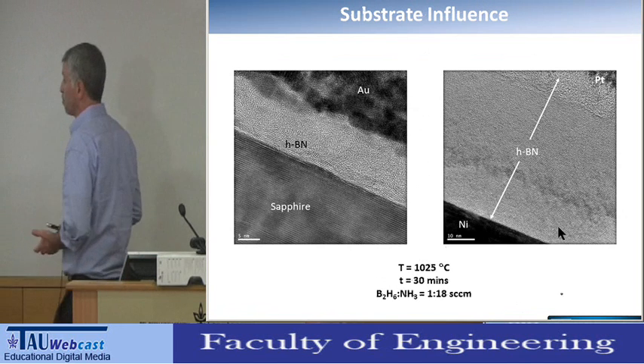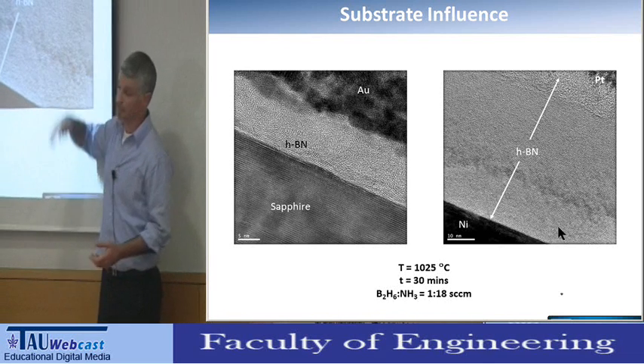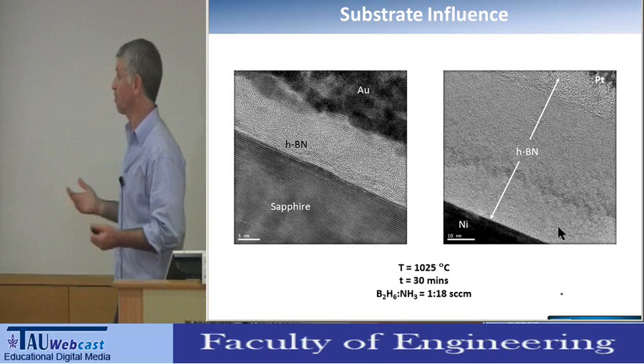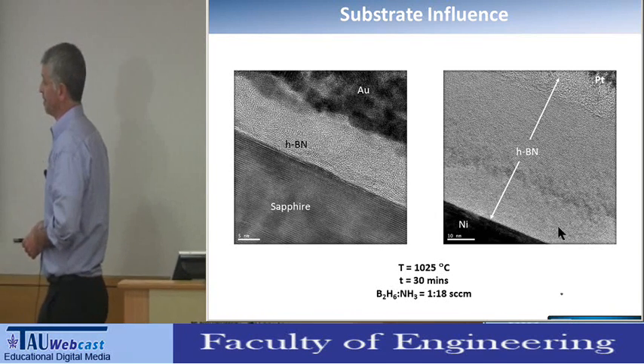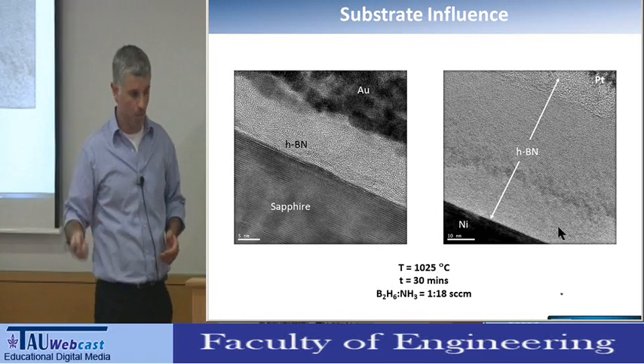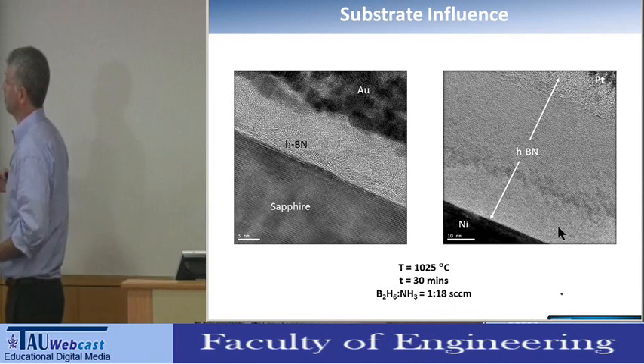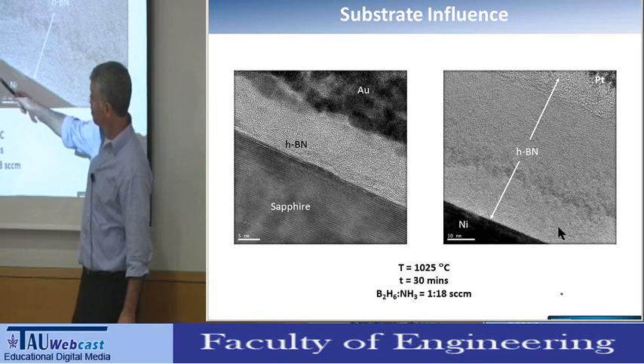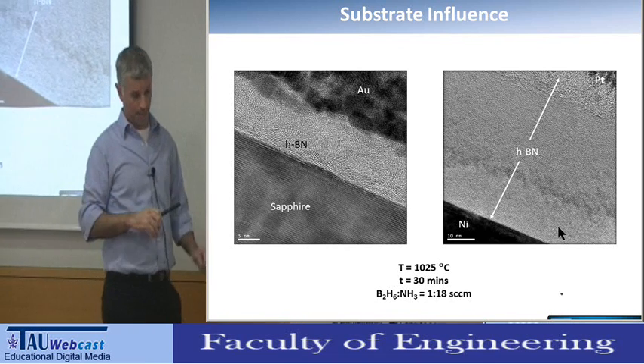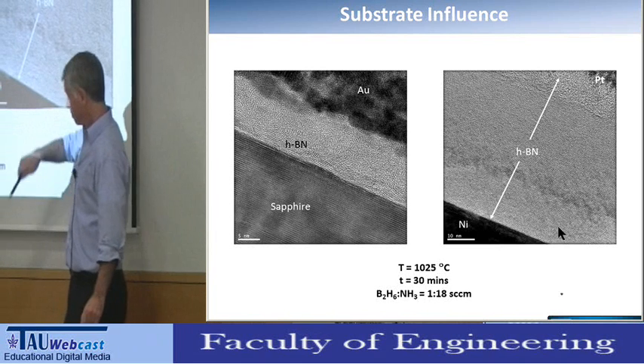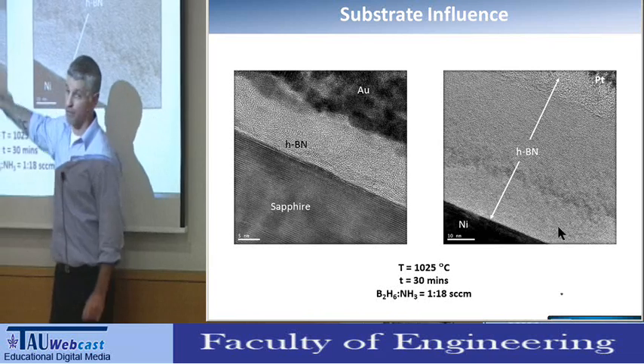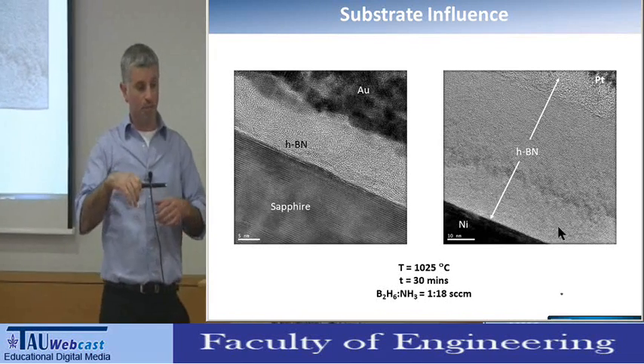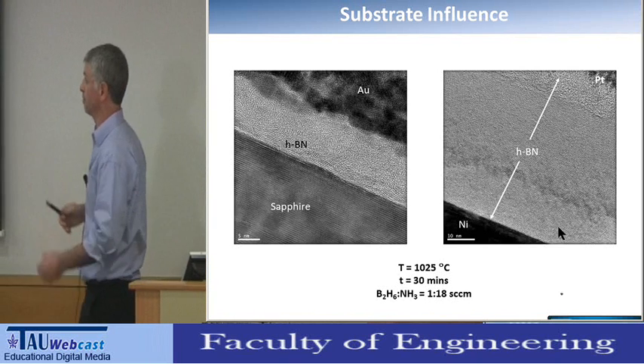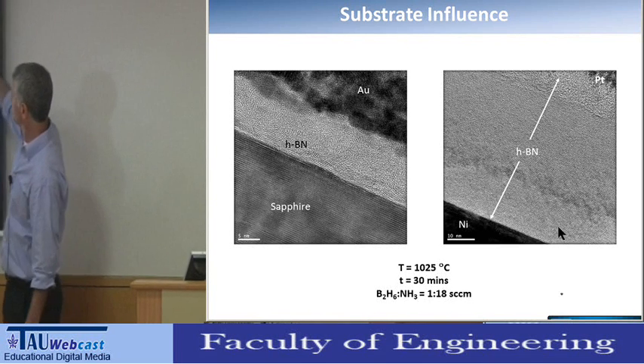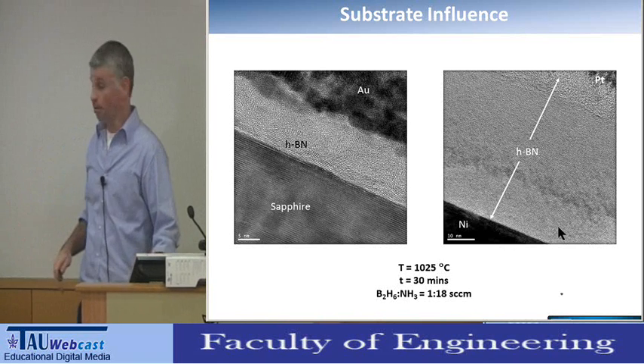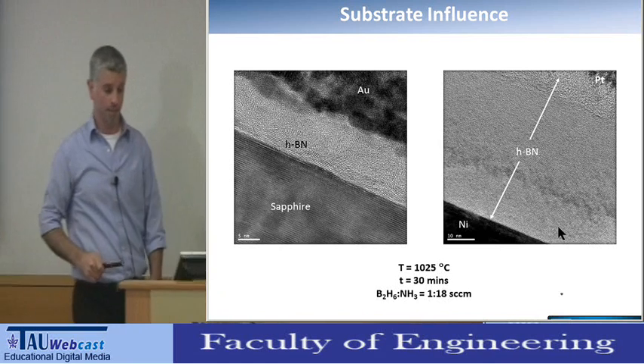And so then we ask, if we can grow such thick materials with very nice planar structure, what's the role of the substrate? What's the role of the nickel? And so then we tried to grow the same films on different materials like sapphire, silicon dioxide, quartz, etc. And we noticed that we just can't do that. You can see here a cross-section TEM image of two films that were grown in the same CVD process, one on nickel, one on sapphire. And you can see that on sapphire you have only partial order very close to the surface, but then you have what is usually called in the literature a turbostratic structure, a disordered and nanocrystalline structure. But here on nickel, you have a planar HBN structure almost all over the thickness of the film.